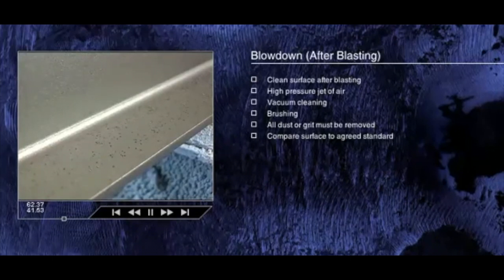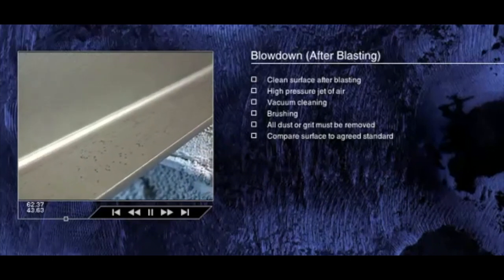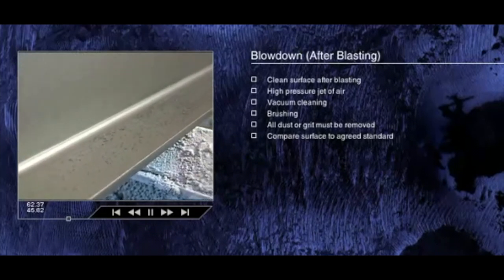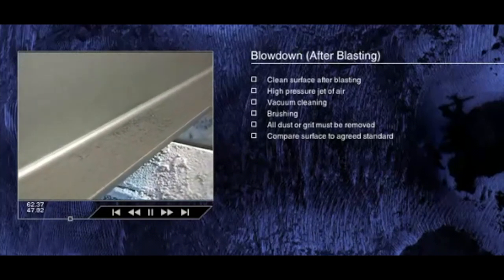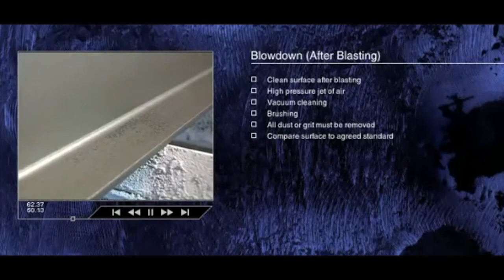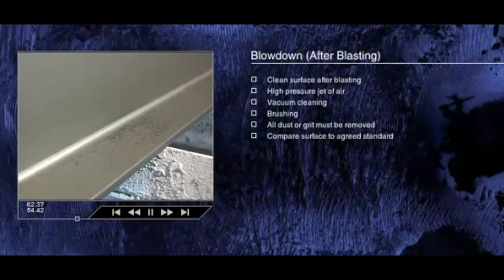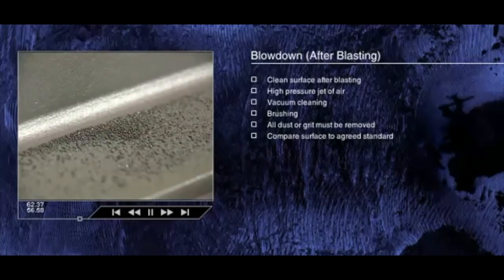When dust or grit is not completely removed, it often remains hidden in crevices or corners. It can be disturbed by the high pressures of the paint spray stream and can be distributed into the paint film, causing a poorly adherent paint layer or an incomplete film.